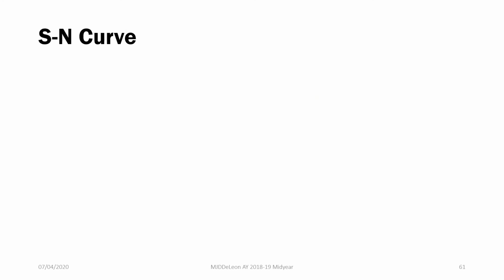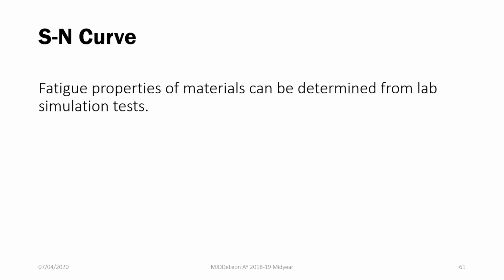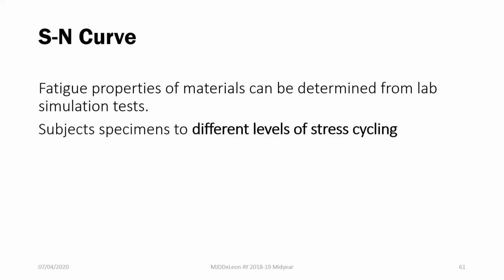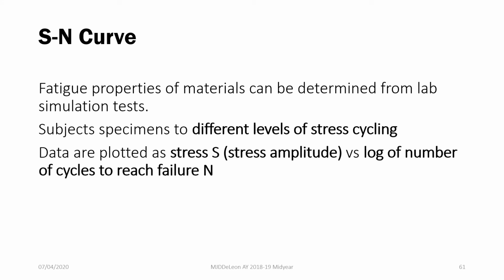So, to determine the material's properties under fatigue, we usually construct the SN curve of your material. We can get the fatigue properties from lab simulation testing, such as fatigue testing as seen in the previous slide. We subject your material to different levels of stresses, then we plot the number of cycles before failure versus the stress of the cycle.